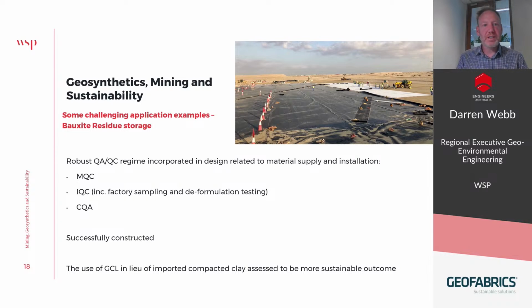So then we got to construction, and we developed a design that included a robust QA/QC regime related to material supply and installation. That included the IQC stage, the independent quality control testing done at a third-party laboratory, and that included sampling from the factory and also specialist deformulation or fingerprint testing on the geomembrane to identify if the supplied material had the same stabilizers and additives as the sample provided for the durability testing.